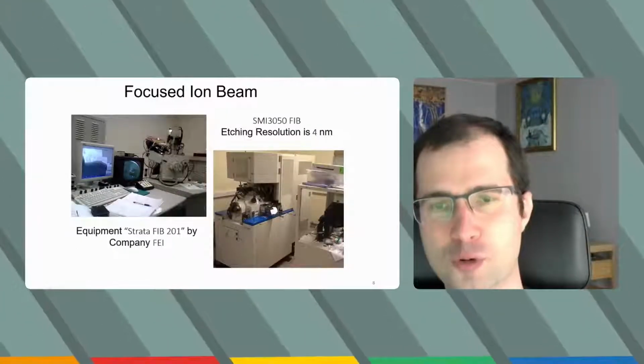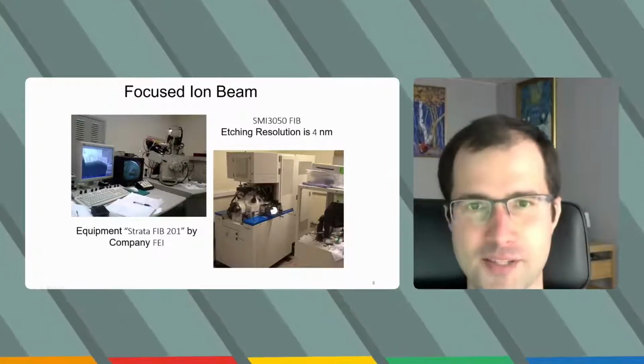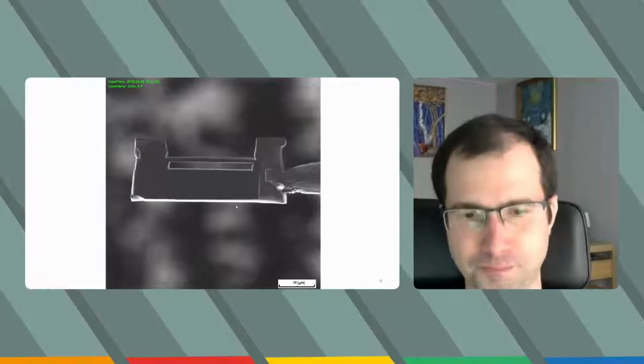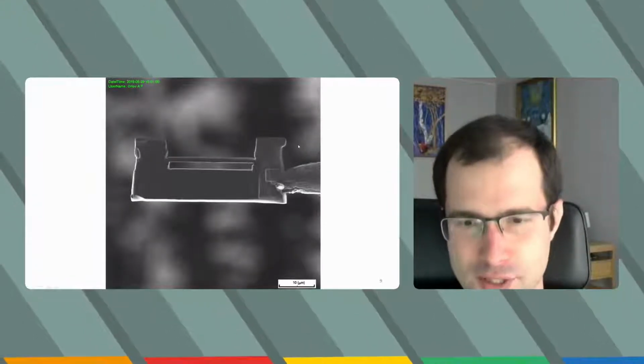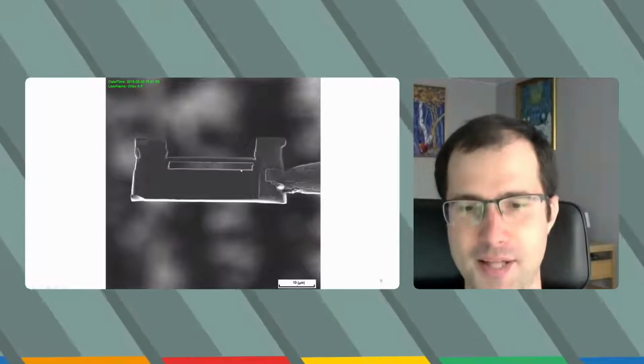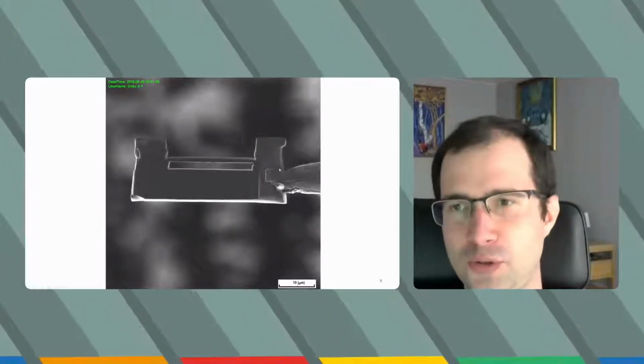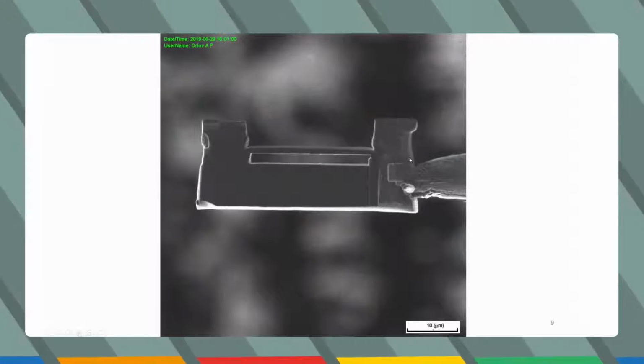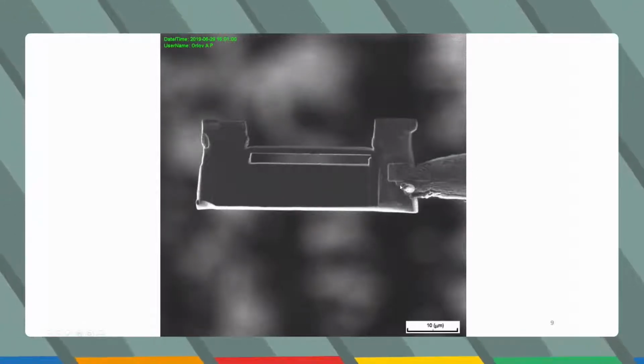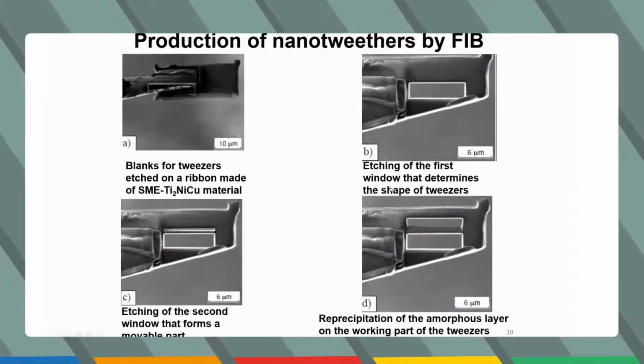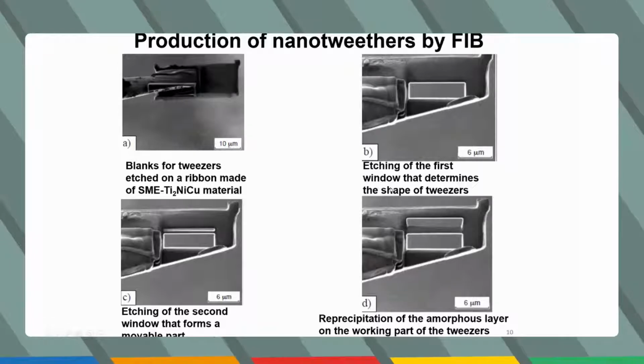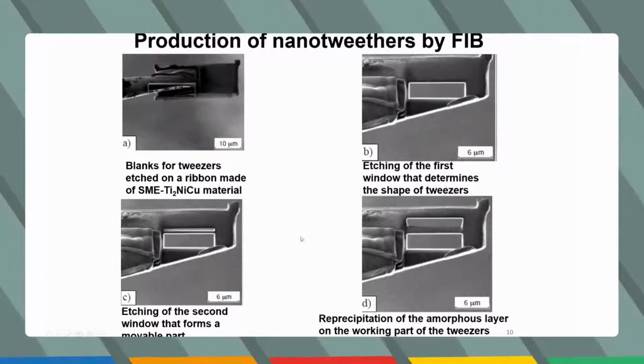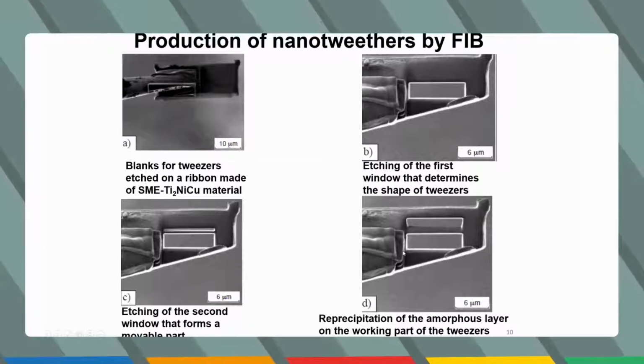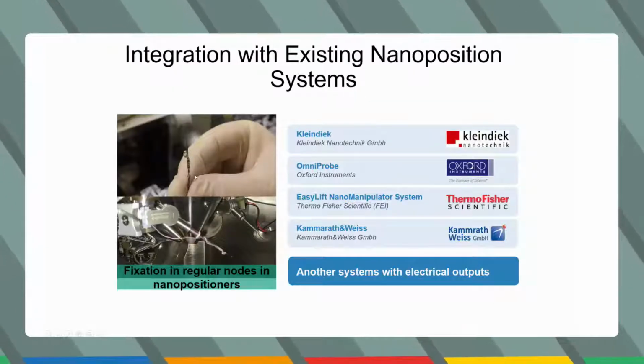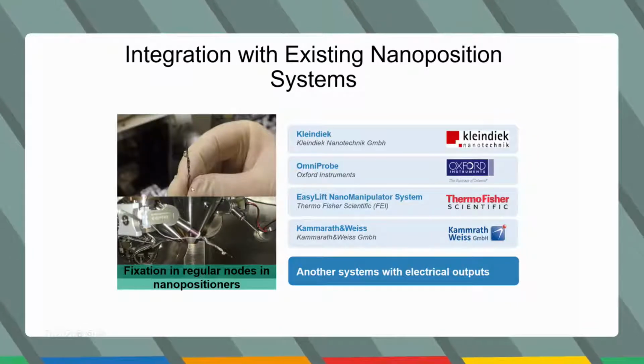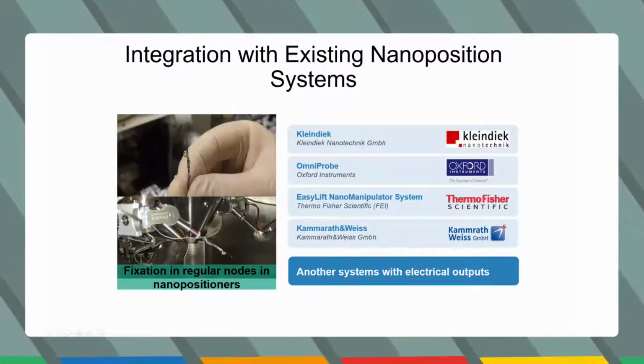Nano tweezers are made with focused ion beam equipment. There are examples of this equipment in our team. This equipment can visualize objects, cut the metal, and deposit material. Here you can see a titanium 2 nickel copper ribbon attached to a tungsten needle by Pt deposition, platinum deposition. Here you can see several steps of the production of the nano tweezers by FIB milling. At the last step, the bimetal structure is formed. These shape memory effect nano tweezers are mounted on needles and easily integrate with commercial nano manipulators.